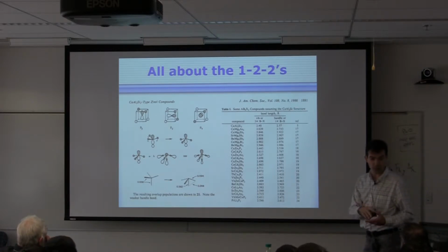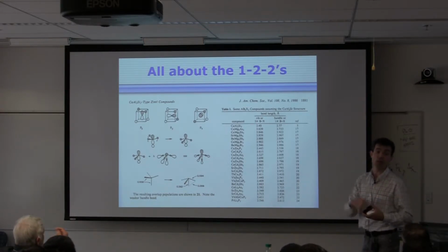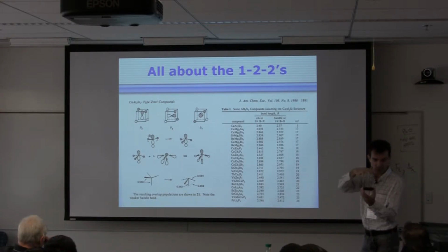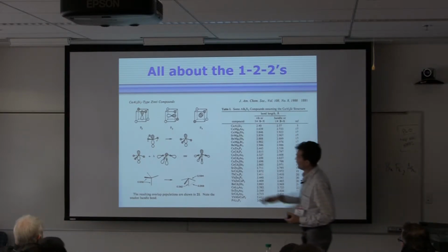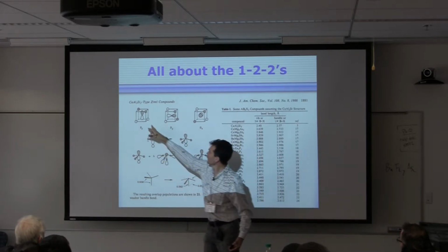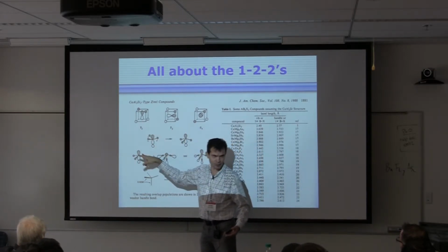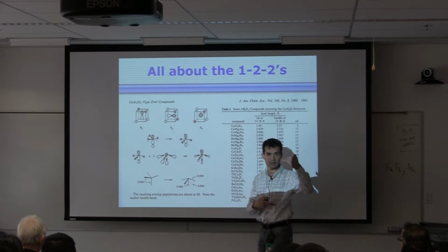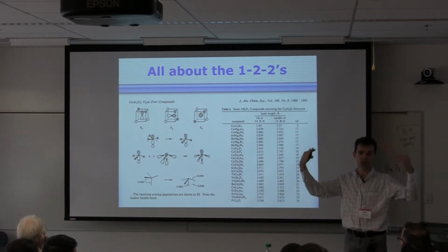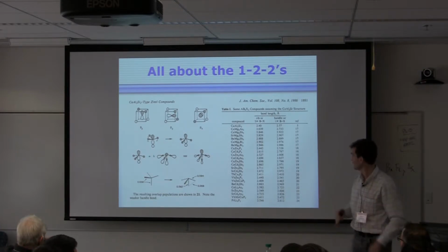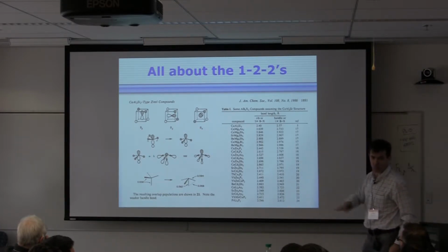Barium and potassium almost have the same ionic size, but this is an isoelectronic substitution, removing a little bit of electron, and that forces it to happen. And of course, the preferences here have also been addressed. You have the p orbitals, the s orbitals, the hybridization, which element would take the tetrahedral site, which element will take what they call the umbrella site, based on electronegativity, and analyzed in beautiful detail, in a very beautiful work.